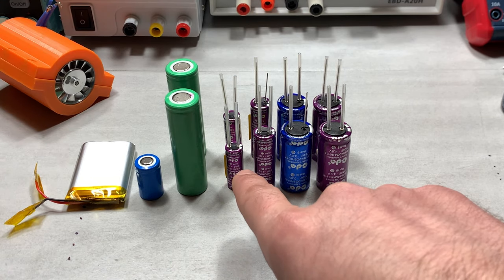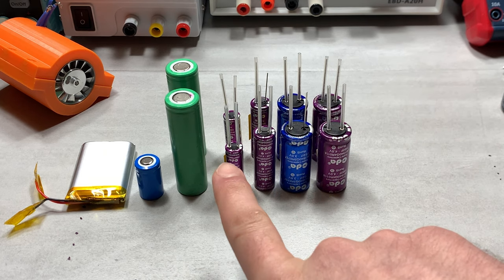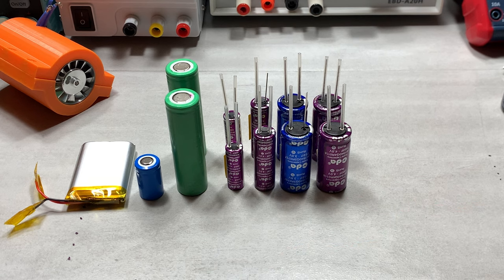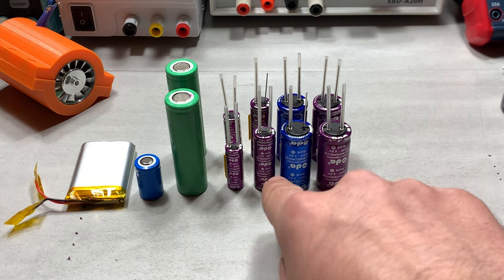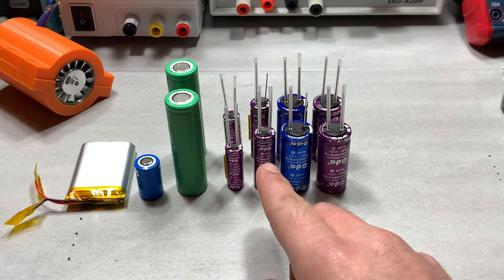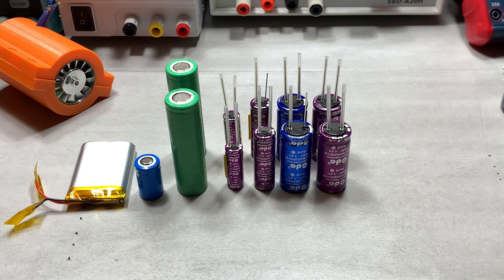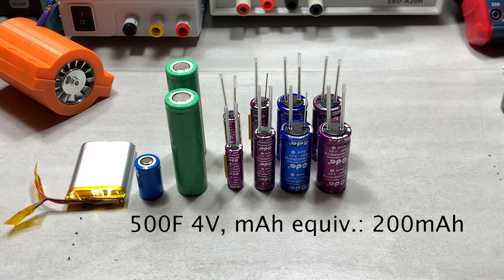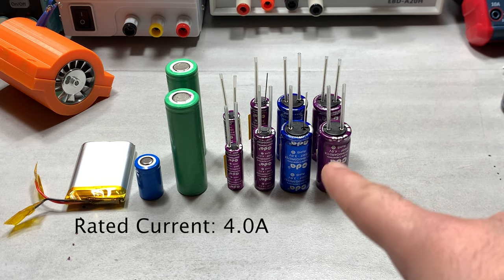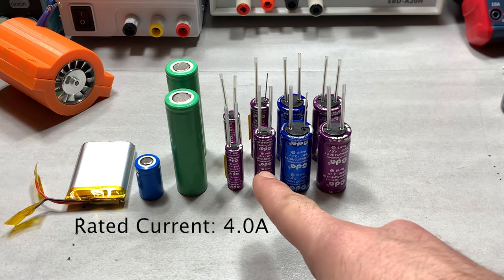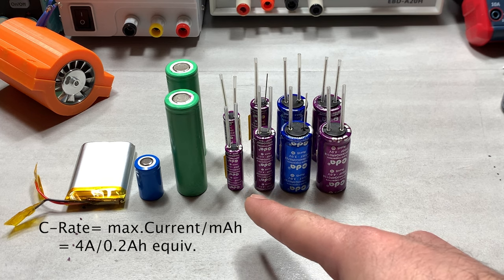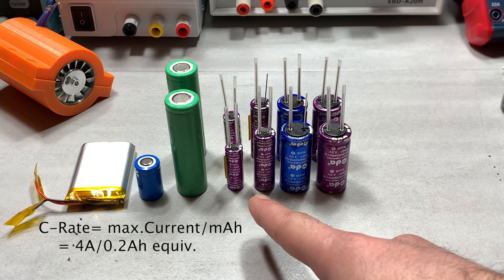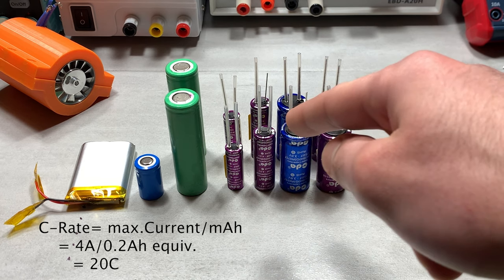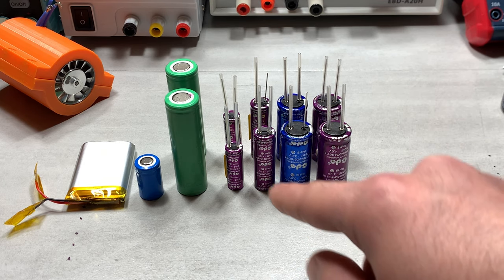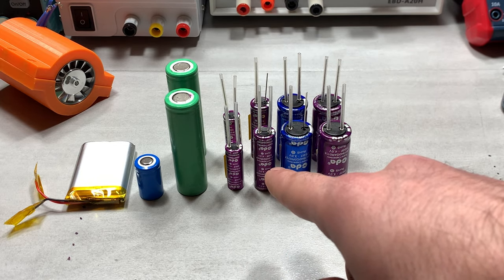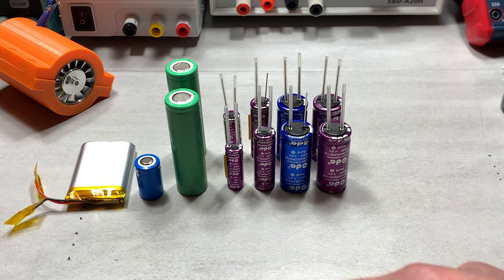So starting off with this little 200 farad 4 volt, and I know I said little, this is far from being little, but starting off with this 200 farad 4 volt supercapacitor, and actually this one is not specified in the datasheet, so I'm just going to step up to the 500 one. So with this 500 farad 4.0 volt supercapacitor, we have a milliamp hour equivalent rating of 200 milliamp hours with an operating rated current of 4 amps per cell. And we can find that charge rate by just dividing the 4 amps by 0.2 amps, so 200 milliamps, which gives us a C rating given the rated current of 20C, which means you can charge or discharge this at 20 times its equivalent capacity in terms of the amount of current you're pulling or putting into it.